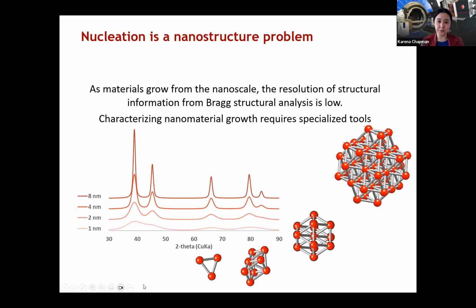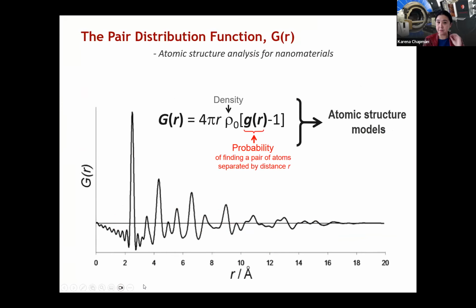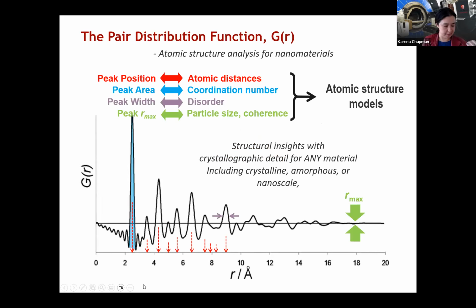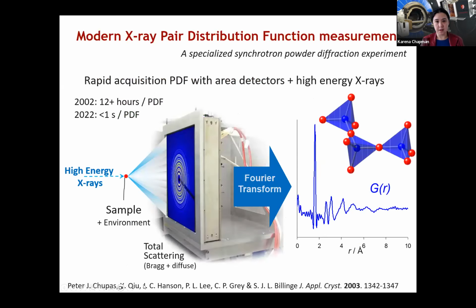As we reduce materials to the nanoscale, we have small particles and very broad Bragg peaks, so we can't use Bragg diffraction to characterize this process. This is where we use the pair distribution function method, giving us detailed atomic scale information for nanomaterials. We can pull out information about atomic positions, the coordination number from peak areas, and information about particle size, applying structural models to all of this.